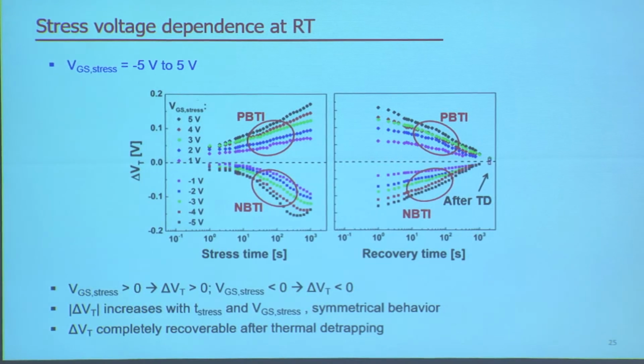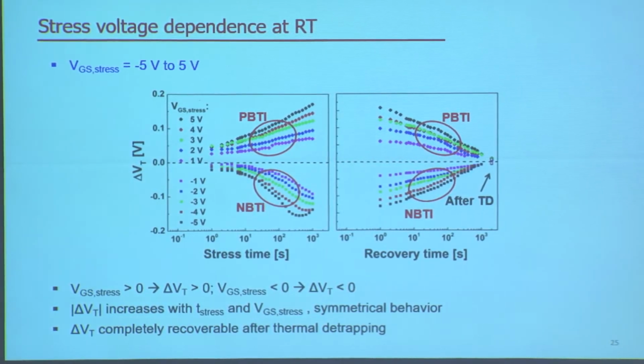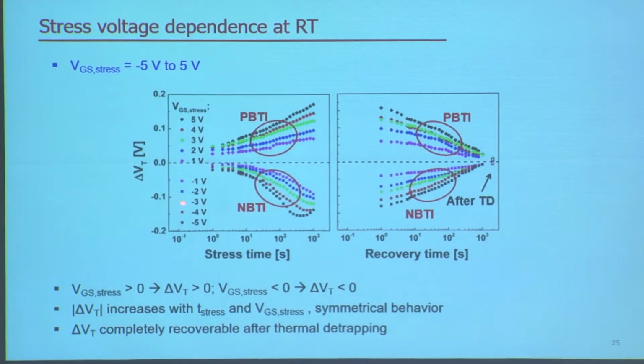What we first look at is, at room temperature, the stress time dependence of delta VT. And we use 10 different stress voltages at room temperature and see how delta VT changes over time during stress and also during recovery. What you will first observe is that under positive bias stress, you see a positive VT shift, and for negative bias stress, you see a negative VT shift. And they have this very symmetrical behavior, and as we increase the stress time, the magnitude of delta VT increases. And delta VT also increases as the magnitude of the stress voltage increases.